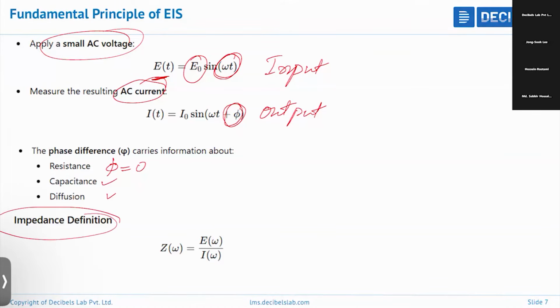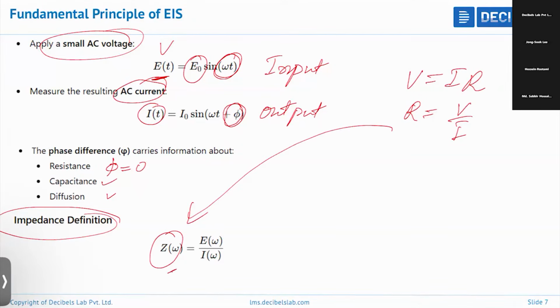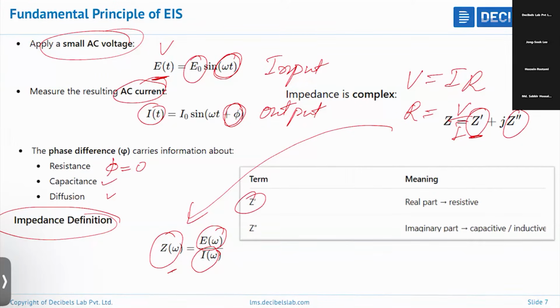So overall, the impedance equation: we know that this is voltage and current, so V is equal to IR, and R is equal to V by I. So the impedance Z with respect to the frequency is equal to the input AC voltage divided by the output AC current. That Z is represented by the real impedance and imaginary impedance. The real impedance corresponds to only the resistive behavior of the battery. If there is no capacitive or inductive behavior in the battery, then whatever resistance you get is just the real resistance. If the battery involves capacitive or inductive components, then we have this imaginary component, Z double prime. I'll be discussing that in detail.